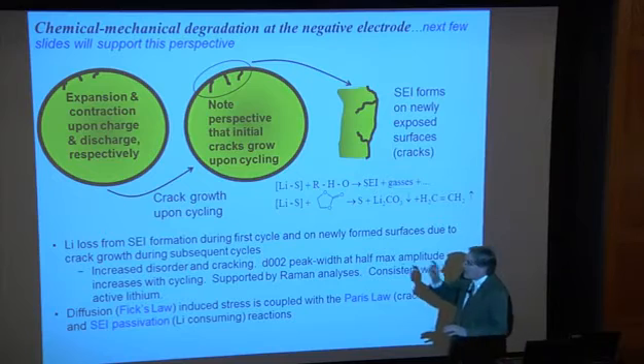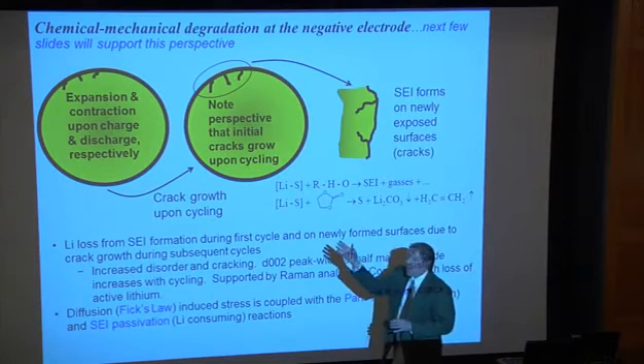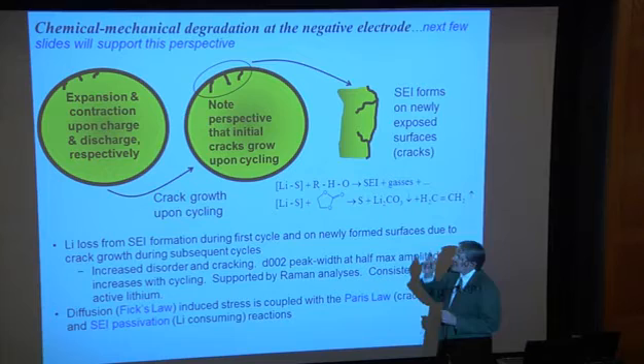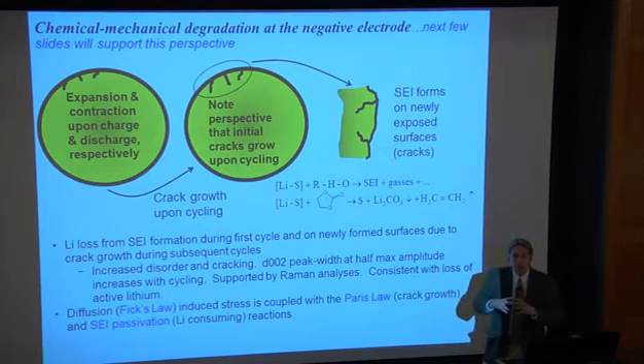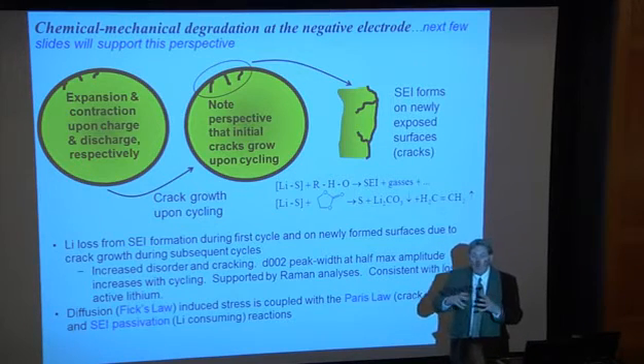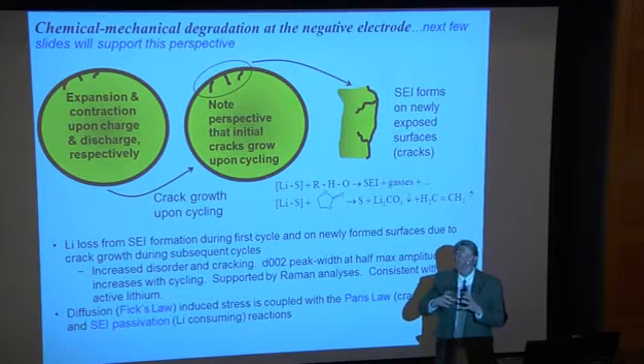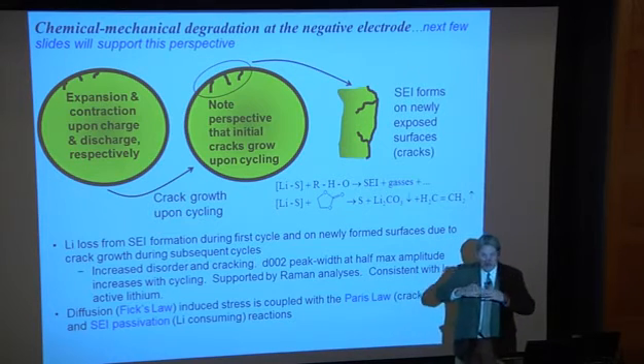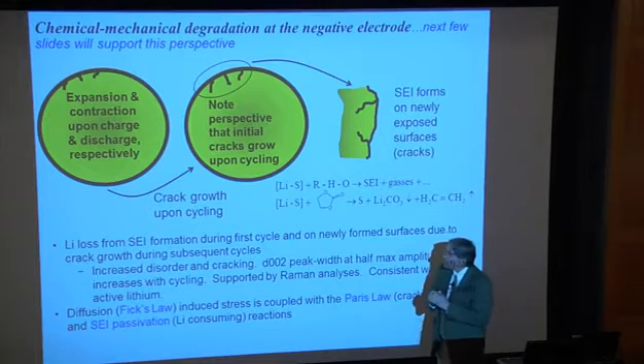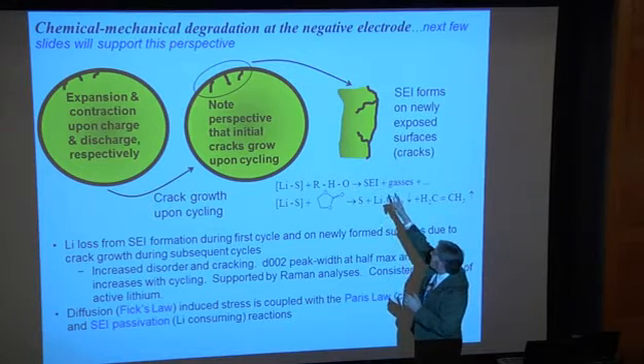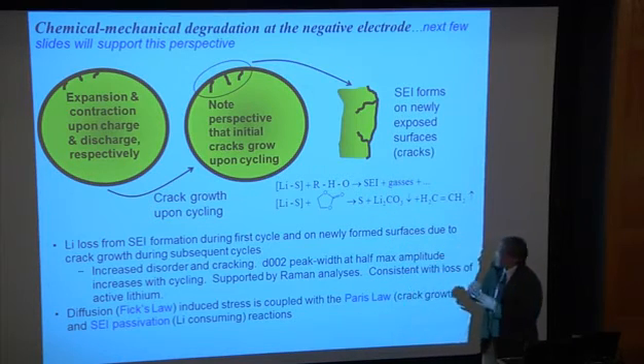So I've talked a bit about degradation. This is a sort of a pictorial explanation of it. Starting on the left, we have expansion and contraction, so solid mechanics play a large role there. And we find that the stresses on discharge are very high at the surface, the tensile stresses that tend to crack then the particle at the surface. And what can happen then, at a blow up, you can see here these cracks start to grow in.